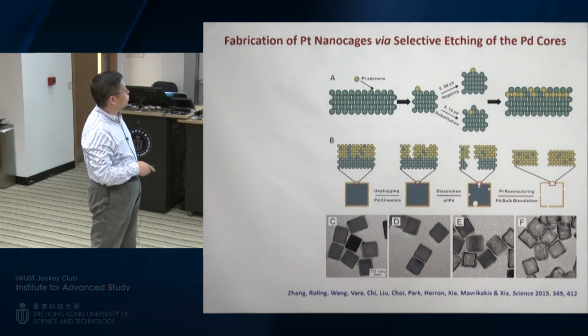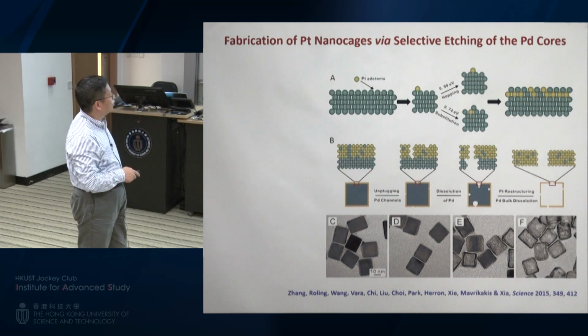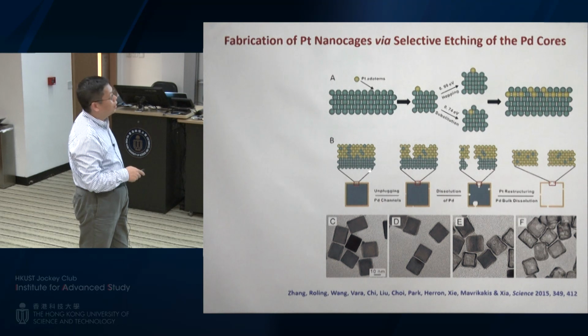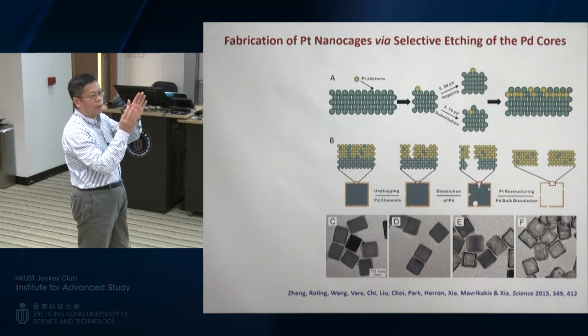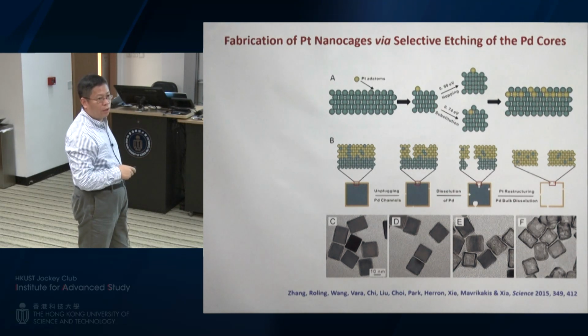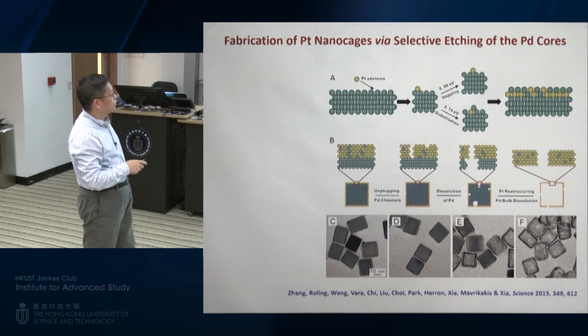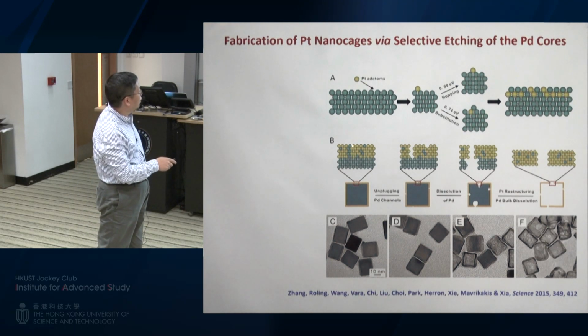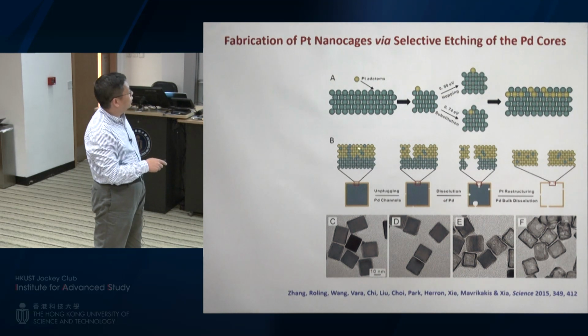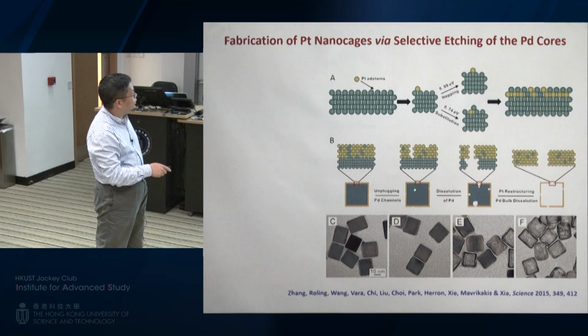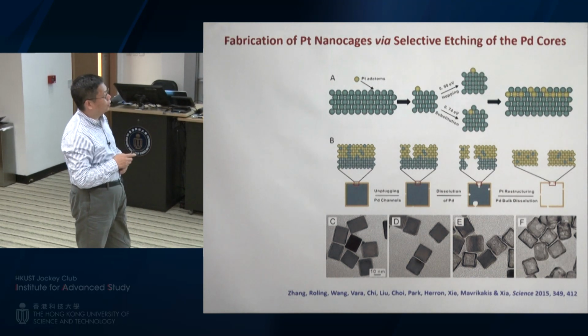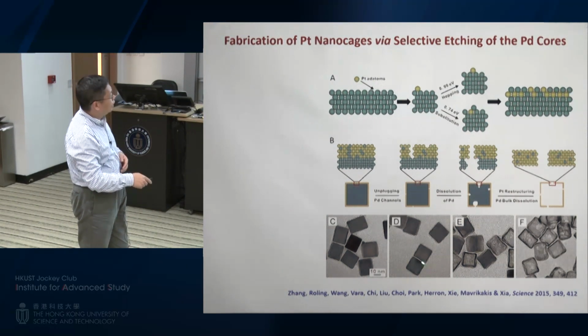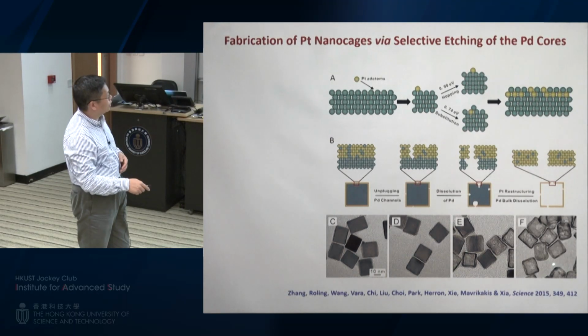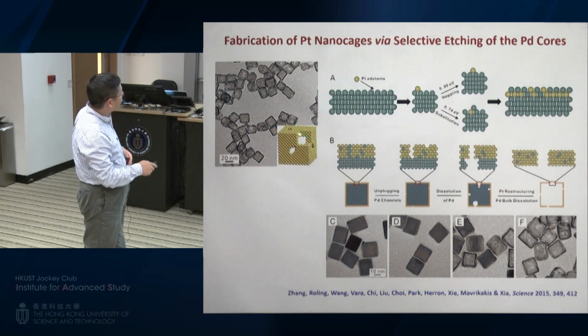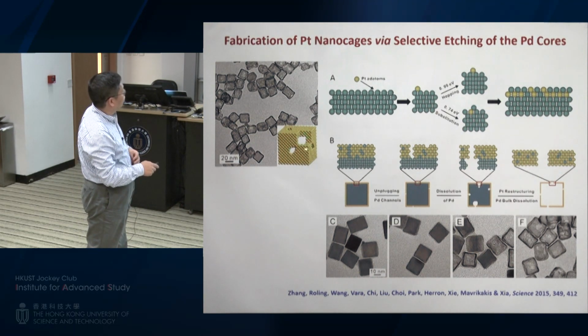So once we have made this core-shell structure, you can etch away palladium. The reason is very simple. Whenever you deposit metal A on B, it's kind of naive to think about a pure A core and B on the shell. They are always going to have interdiffusion and mixing. So there is always going to be some palladium mixed in the platinum shell. That can serve as a channel for etching, and eventually you can etch away the palladium to obtain essentially pure platinum nanocages. In this case, this just shows you TEM images along this etching process, and finally you can make almost 95% pure platinum nanocages.